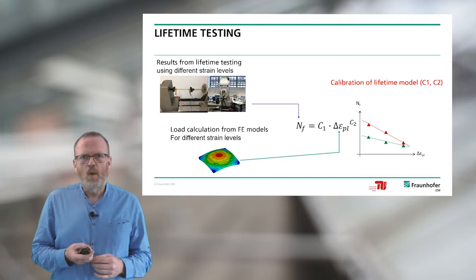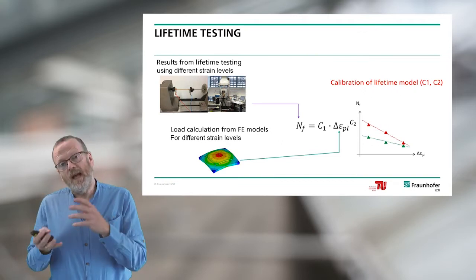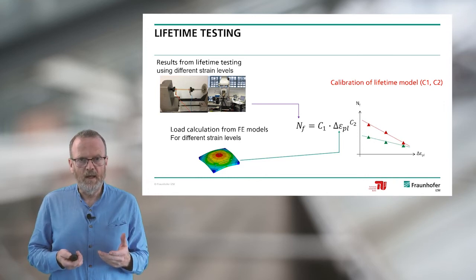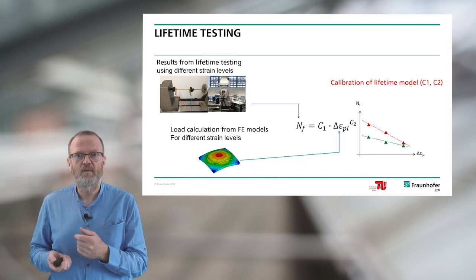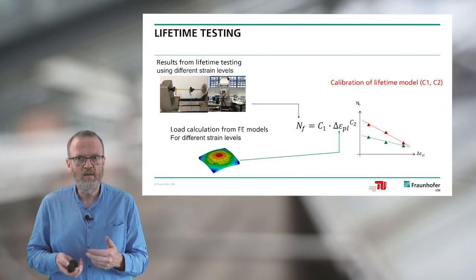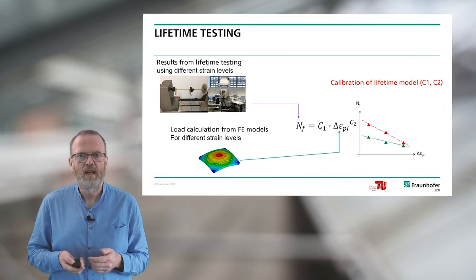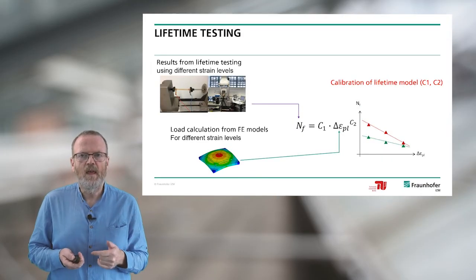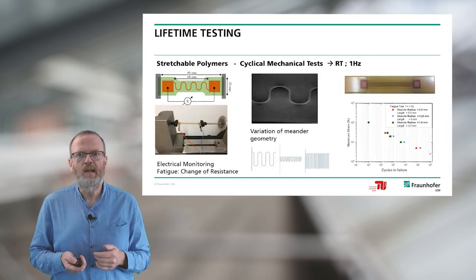Using the lifetime cycle test methods with the combination sample of polyurethane and copper, and varying the amplitude and frequency, we determine the critical value of numbers to failure. You can see in the middle of the diagram the Coffin-Manson model, and what we determine from this materials data are the parameters C1 and C2, which are important for the finite element modeling. We also use calculation from the tensile and biaxial test data to analyze the elastic-plastic strain, giving us both plastic strain and cycles to failure.